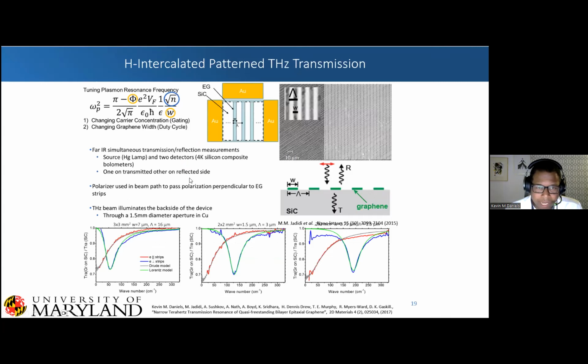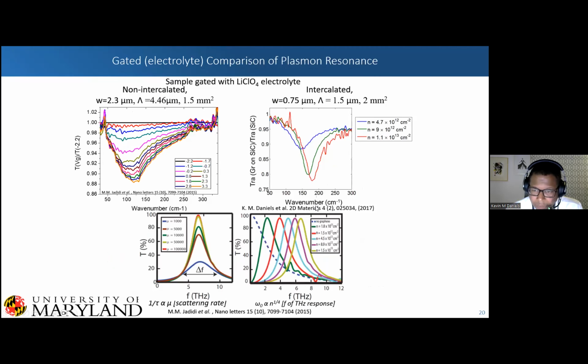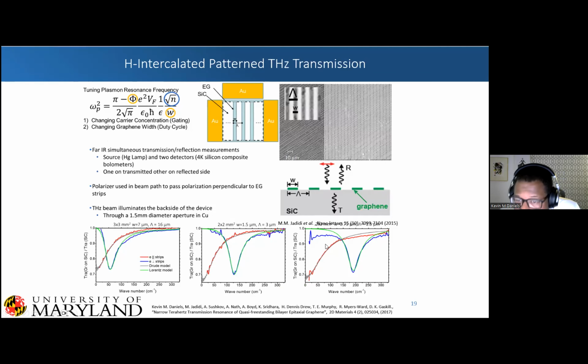Now, we patterned these samples in a few different configurations. Unfortunately, some of that is blocked off. I noticed these structures down here are 0.75 microns with a pitch of 1.5 microns. But as you can see, we're able to shift going from around, I think it's like 1.7 terahertz all the way to around 5 terahertz, simply by changing the width and the period of our grating.